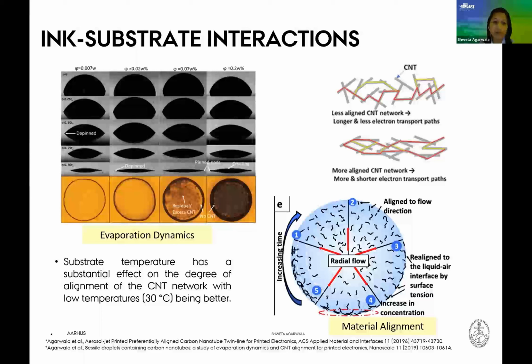We deal with a lot of issues, one of the most common being the coffee ring effect, wherein, just like your coffee mug, most of the material basically transfers and gets collected at the rim rather than at the center. So there's no homogeneous distribution of the material once you print it. The other issue is alignment. Sometimes the alignment of the materials, for example, carbon nanotubes or graphene sheets, gives you better electronic properties and enhancement of functionality, which gets destroyed when you're trying to print them. And we have been looking into material alignment, evaporation dynamics, surface tension issues, ink-substrate interactions in order to understand what should be the right recipe for a particular ink on a particular surface to evade these kinds of issues that we face.